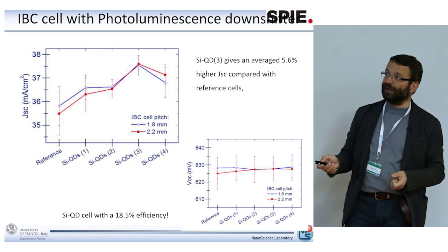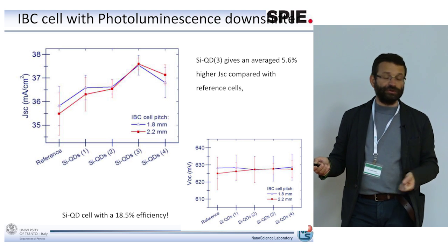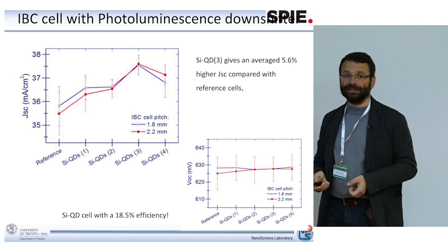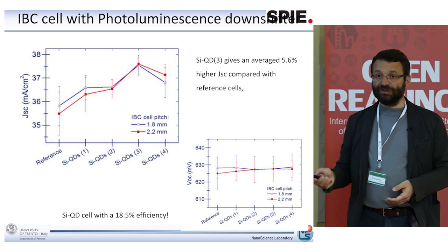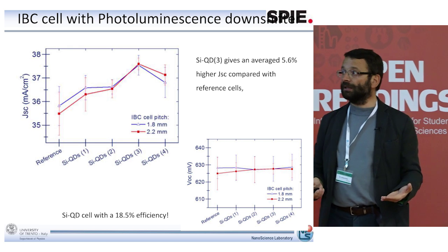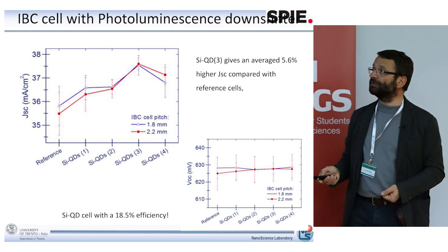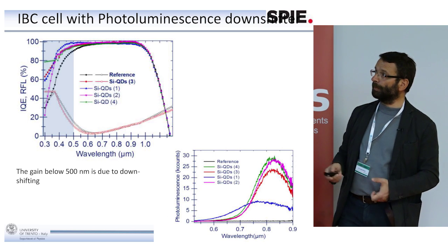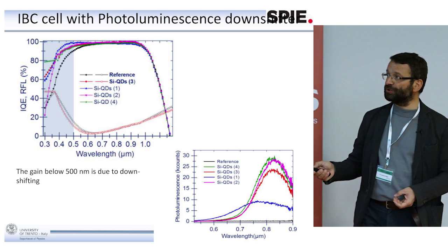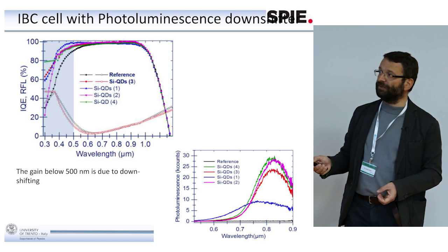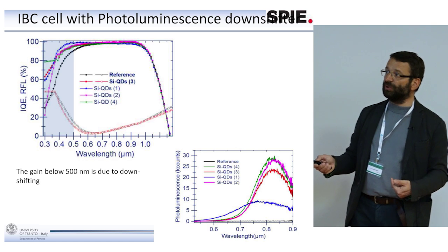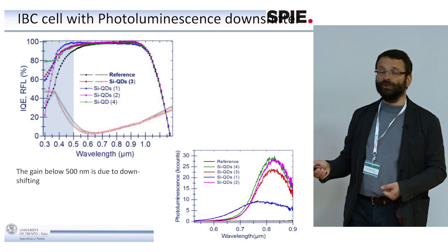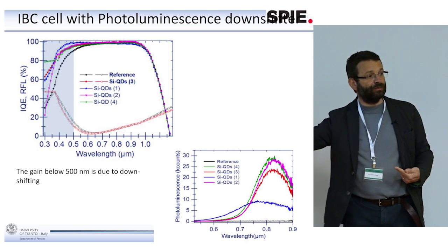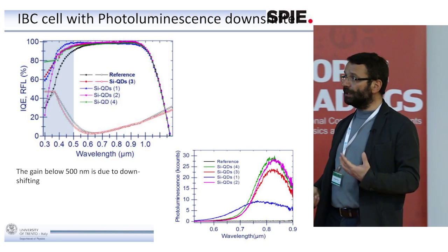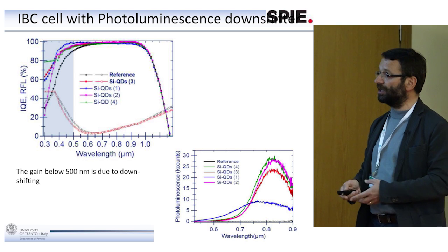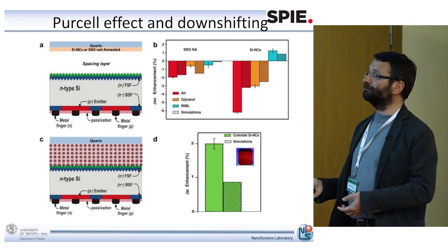But what is interesting is that the short circuit current, here is the short circuit current density, is increased when the nanocrystals are deposited on top of the cell. And so now if you multiply this by that, you get that the overall efficiency of the cell has been improved. Here is the internal quantum efficiency versus the wavelength. What you see here is that the internal quantum efficiency is actually improved for solar light in the blue region, where the nanocrystals play the role of shifting the light to the red. So actually, the starting hypothesis has been verified by this fact.